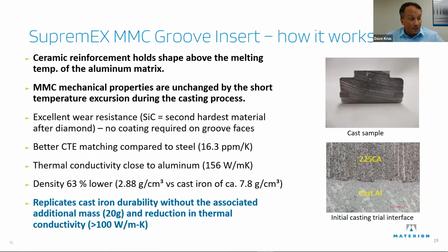So the steel won't expand as fast as the aluminum. So naturally, if you get a piston with a cast insert in there and it gets hot, that aluminum is going to want to pull away from the steel that is not expanding as fast as it. So Supremex is closer to aluminum. It's going to expand and take up that gap more.